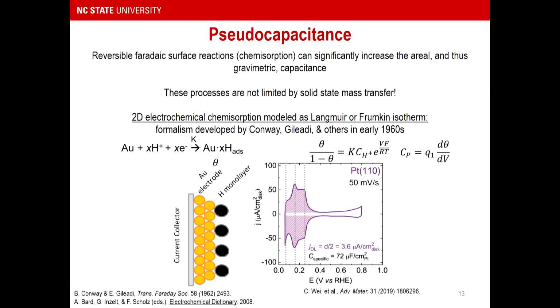So what Conway did is he thought of this as an extension of Langmuir adsorption that could have assigned to it a pseudocapacitance, C_p, that is dependent on the adsorption coverage as an extension of the state of the potential. Essentially a capacitance, but one that was linked to a Faradaic mechanism. And importantly, such processes trend kinetically the exact same way as a double layer process would. For example, your peak currents would vary linearly with the sweep rate.